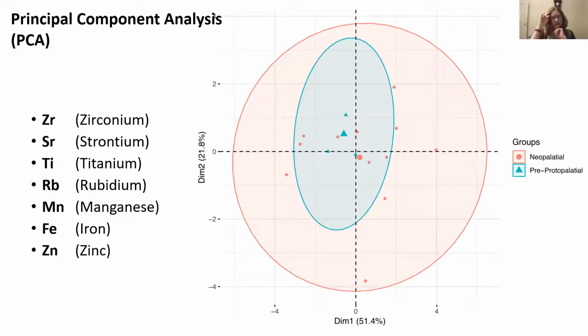One of the first statistical analyses we performed was the principal component analysis based on the elements that you see on the left. So zinc, iron, manganese, rubidium, titanium, strontium, and zirconium. As you can see, the two main principal components, PC1 and PC2, explain 73.2% of the total variability. And the result shows two overlapping ellipses, which indicates that although our number of samples is quite limited, it's just 15 samples, there seems to be a general pattern of consistency and continuity of raw material sources over time.